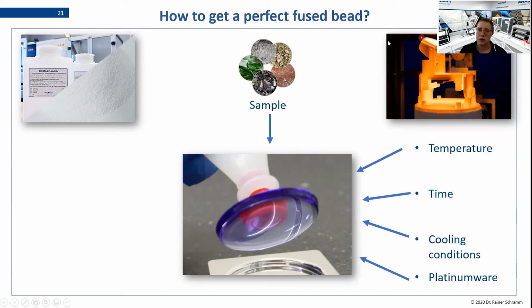So let's first have a look at what we already said about the fusion technique. We already talked about temperature. Adjusting the temperature can be necessary. Adjusting the fusion time can be necessary. Cooling conditions are very, very crucial. Have a look at your cooling conditions when you're having problems with crystallization. And platinum ware. When your platinum ware is not in a good shape, maybe just exchange it for platinum ware that is in a good shape. When you're having scratches, it will cause crystallization. It can cause breaks as well. So this all has to be optimized.